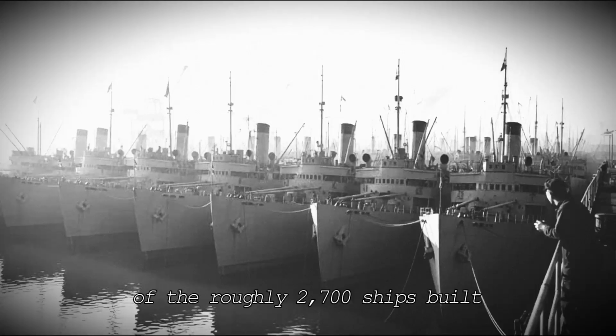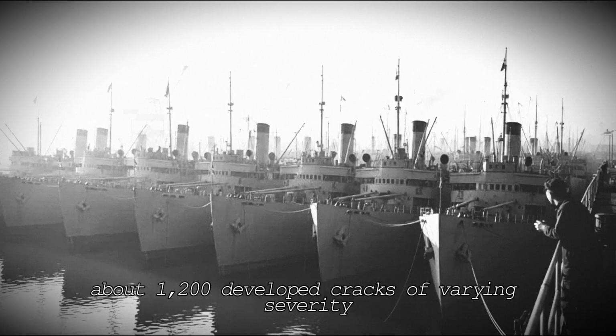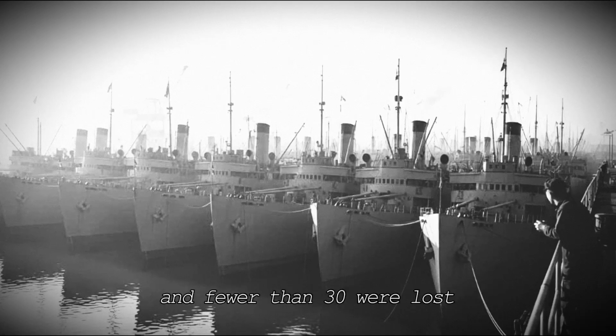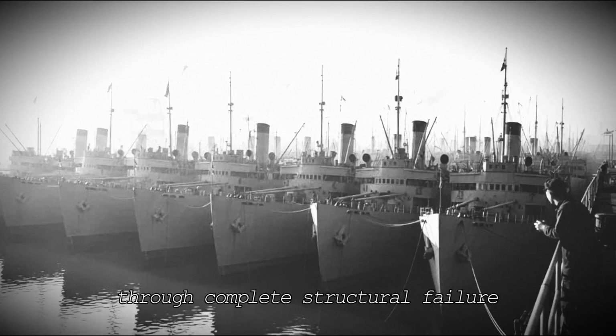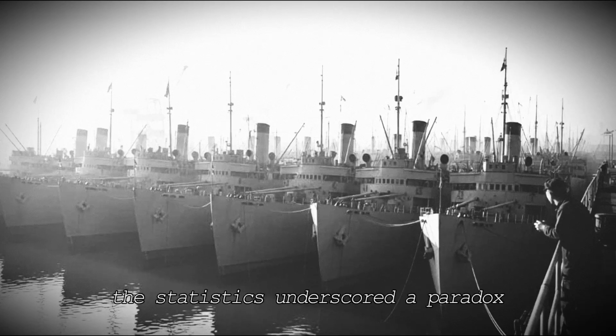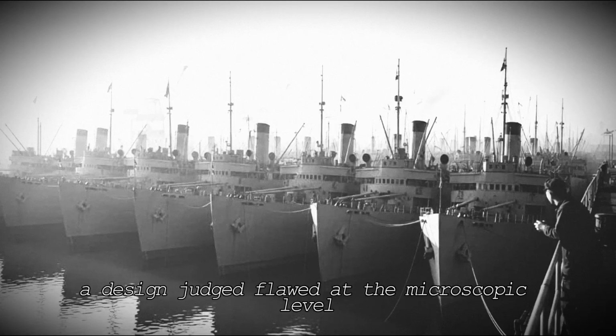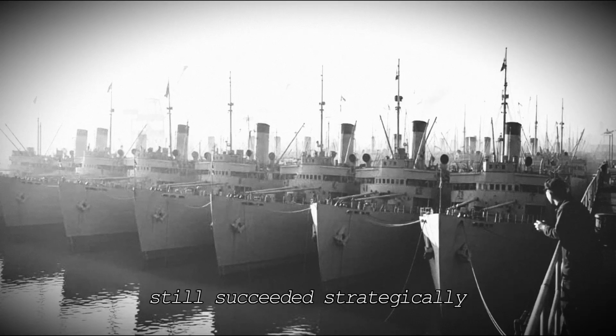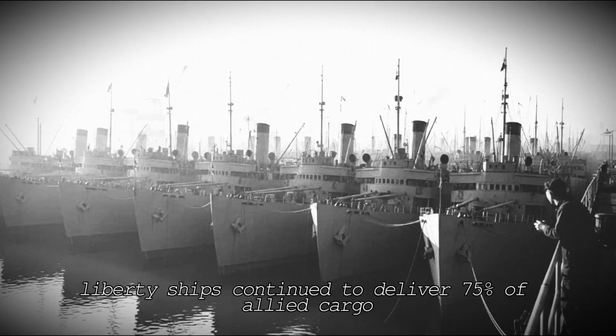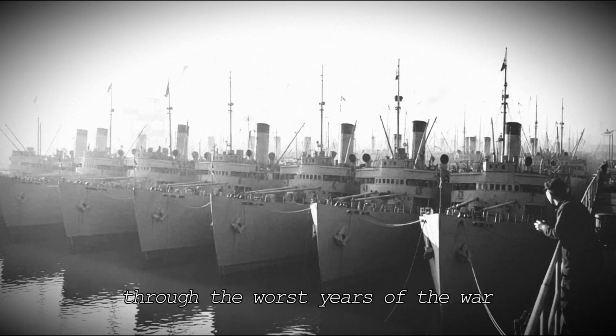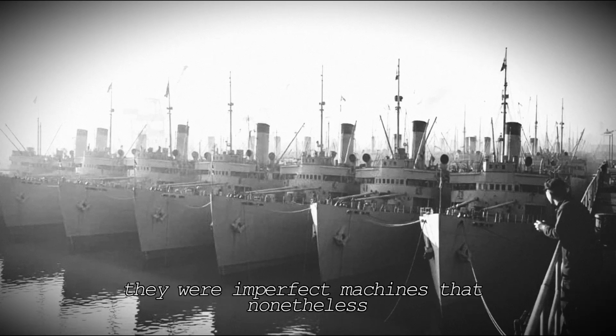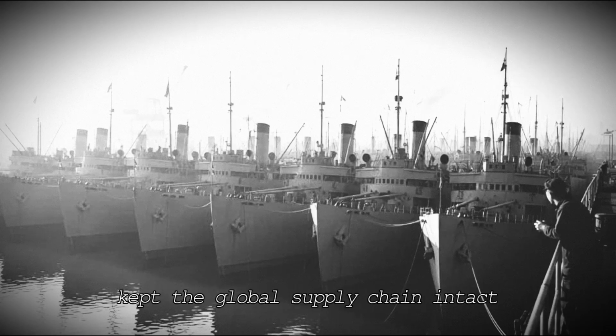Of the roughly 2,700 ships built, about 1,200 developed cracks of varying severity, and fewer than 30 were lost through complete structural failure. The statistics underscored a paradox. A design judged flawed at the microscopic level still succeeded strategically. Liberty ships continued to deliver 75% of Allied cargo through the worst years of the war. They were imperfect machines that nonetheless kept the global supply chain intact.